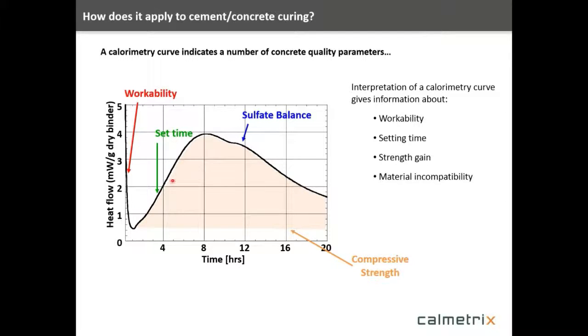At some point, the reaction kicks off, and we can glean information related to the set times on the leading edge of this reaction. The peak is very important. We can look at things like the sulfate balance as it relates to the peak in the curve. And then the area under this curve is important, the absolute amount of heat that gets evolved from the sample that we can get from integrating under this curve. The area under that curve is related to the compressive strength. So there's many things that we can glean from this basic data that we get from the calorimeter.